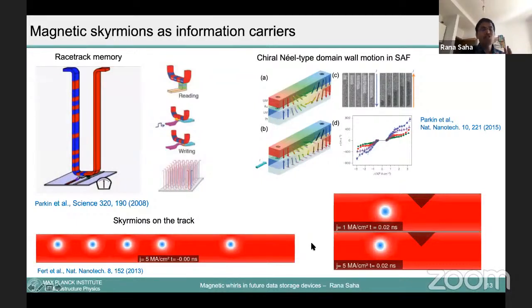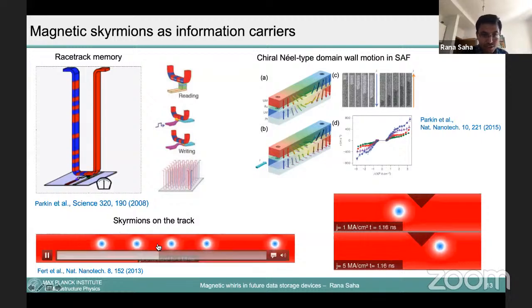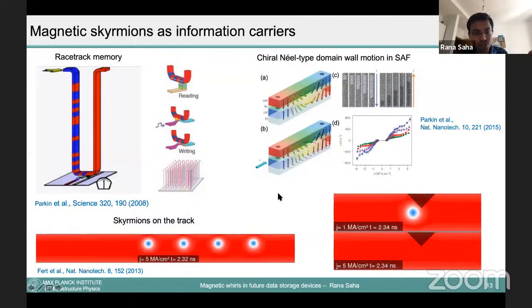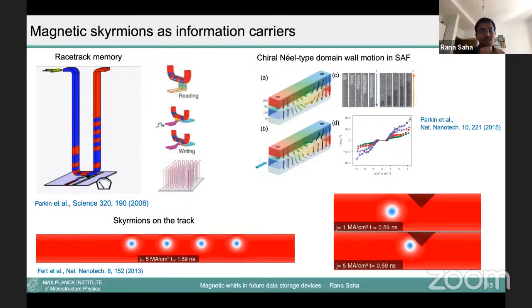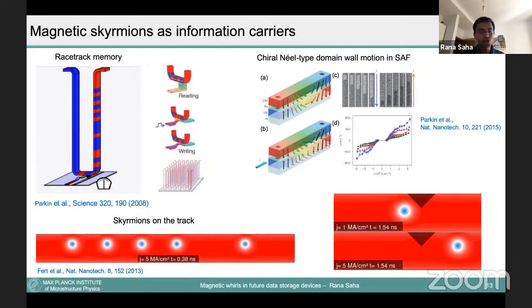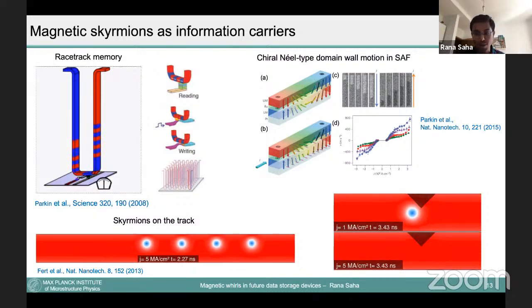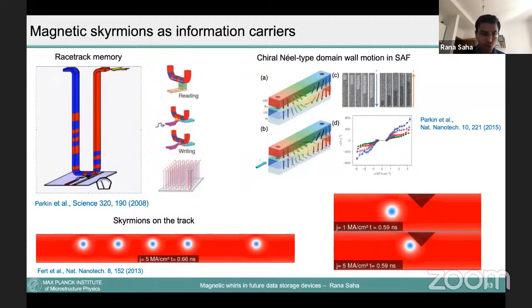So why are these structures important? As I mentioned in the racetrack case, the magnetic domain walls can move. So we can use this chiral structure instead of domain walls. You can see, if we have this kind of structure, this is a simulation, they can move from left to right with the help of current. Because of this tiny nanoscopic size and the equal spacing, you can store more data in a small space. So this is one of the potentials.